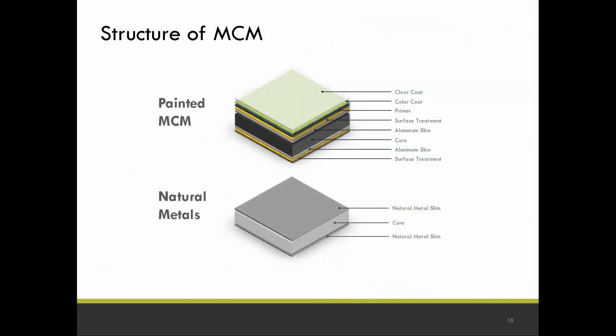This is what MCM typically looks like. Primarily it's painted, which is typically aluminum. So you'll have a core with aluminum skin on each side. There'll be a surface treatment on the finish side, which then has a primer, a color coat, and perhaps a clear coat, not always. The backside will have basically a surface treatment and a primer. The natural metals, which are stainless, zinc, copper, titanium, are basically a core with that natural metal then bonded to each side. There is no finish on those natural metals. If it's copper, it's a plain copper. If it's zinc, it's pretty much a plain zinc, etc.